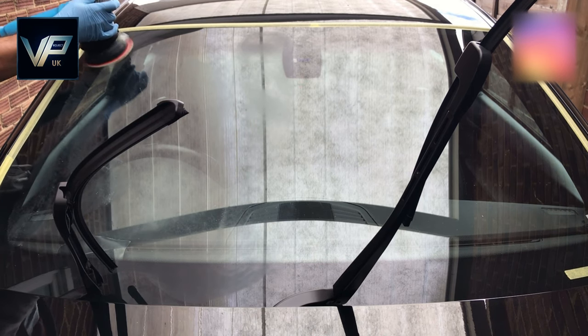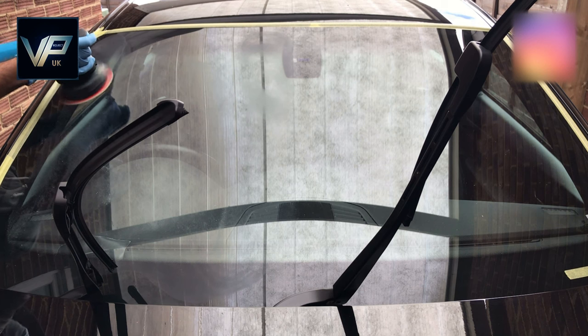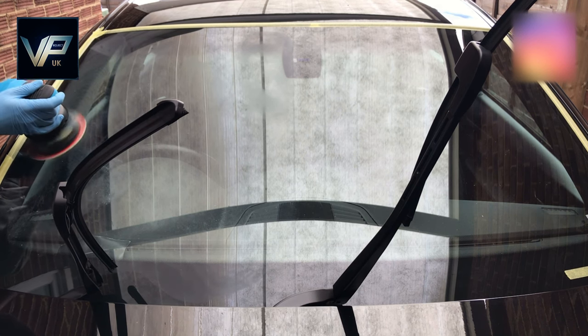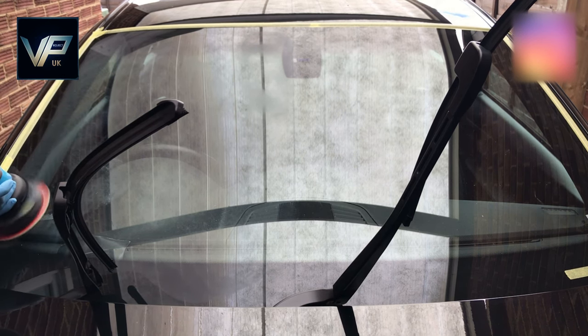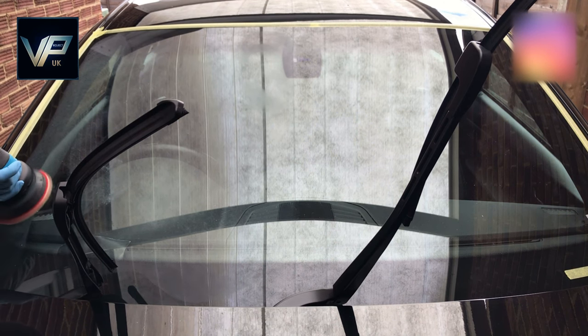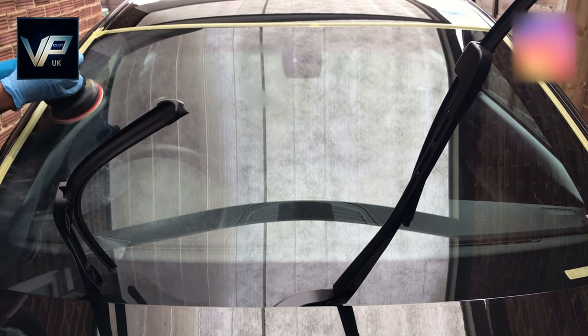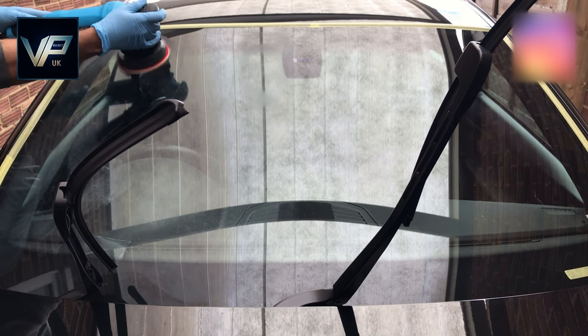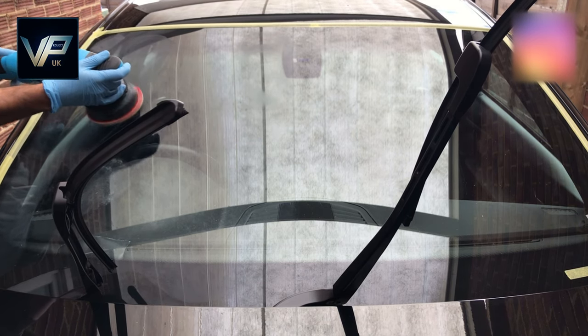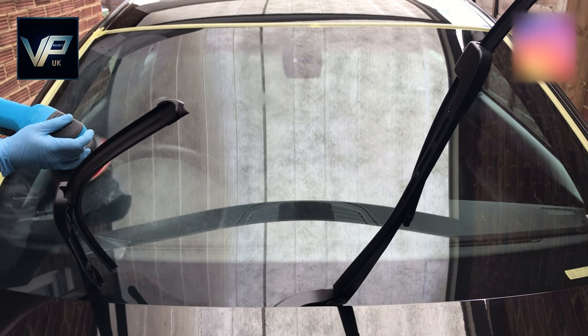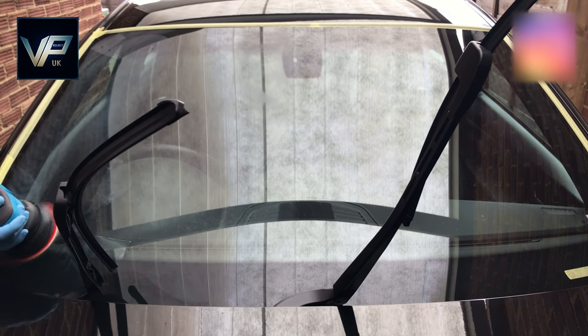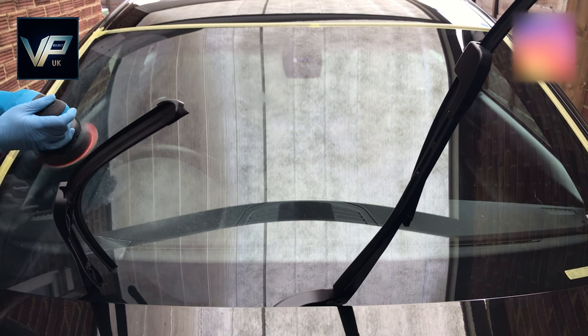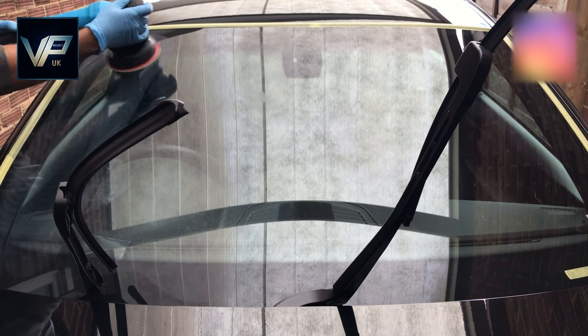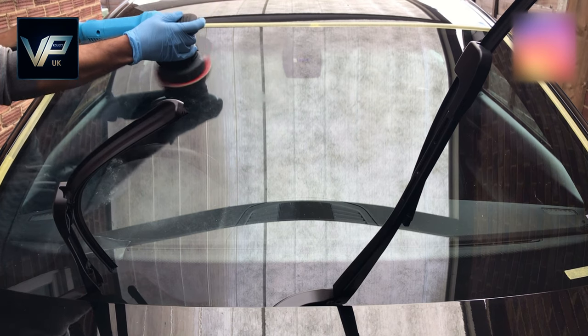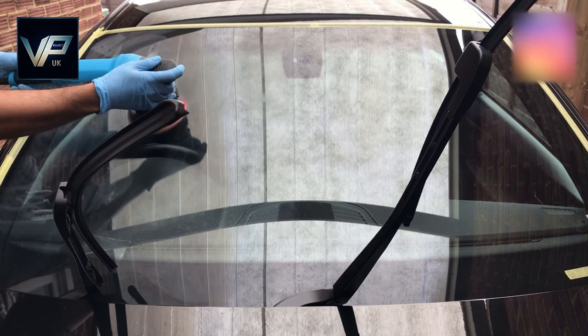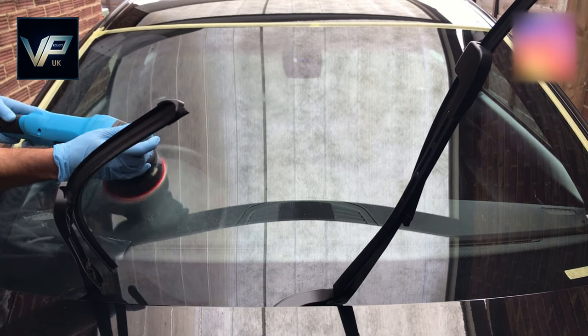As mentioned at the start of the video, CeriGlass is actually capable of removing light and medium scratches from your vehicle glass, so it's actually worth paying attention here and just covering the area as best as possible with a smooth motion. Apply some pressure and just keep an eye on the glass temperatures. The time we're filming this video is actually quite cool and the glass wasn't getting very warm, but you'll see periodically we're testing the glass to see if it's increasing in temperature. One thing that causes glass to warp when you're polishing it is temperature more than anything else, so just keep an eye on the glass temperature.